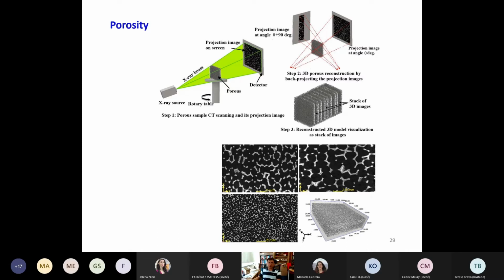You can see an example of 3D porous reconstruction. So an X-ray source is lit and you get the projection image on a screen, and this X-ray machine gives you slices of the different sections of the porous material. Then we use software to put all those things back together. Then you will have an image volume of the whole porous material, and from that we can pretty much accurately measure the porosity of the metal foam that we have.